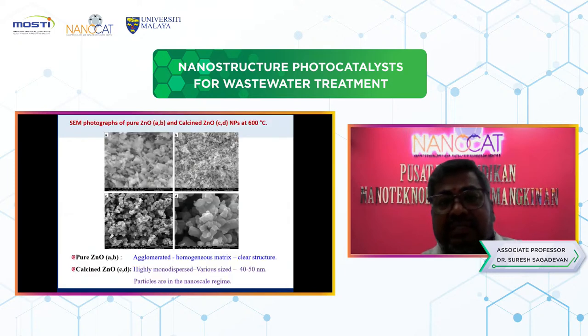As well as that, you can see how the morphology changes with the effect of temperature. Without annealing, which means there is no calcination, look at the images of zinc oxide A and B, which represent an agglomerated but homogeneous matrix. You see very, very small particles or grains on the surface. But when you go for calcination of zinc oxide at 600 degrees Celsius, figures C and D represent highly monodispersed particles. The size ranges from 40 to 50 nanometers. The particles are in the nanoscale.